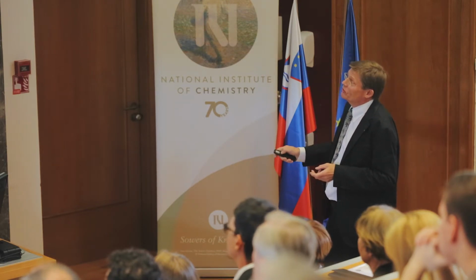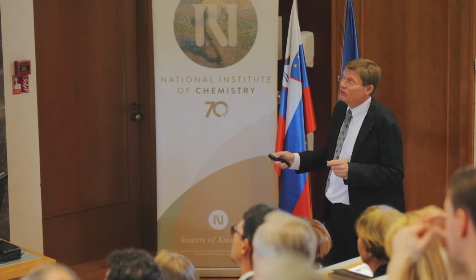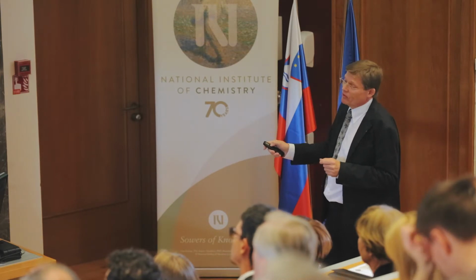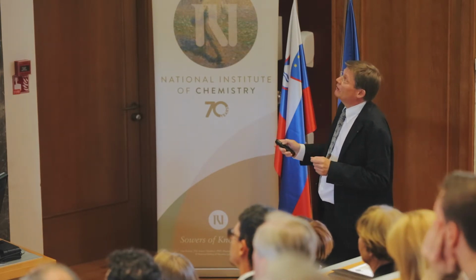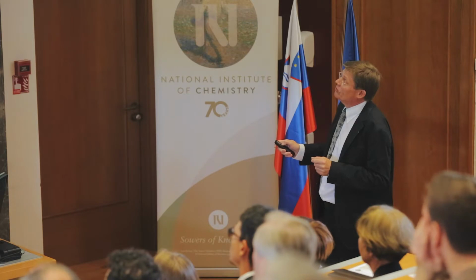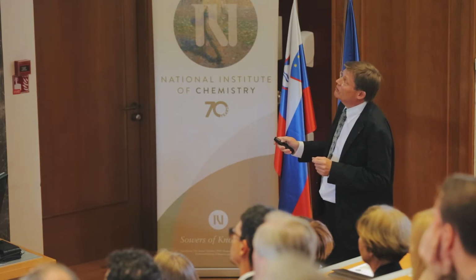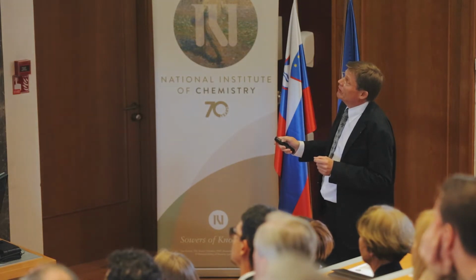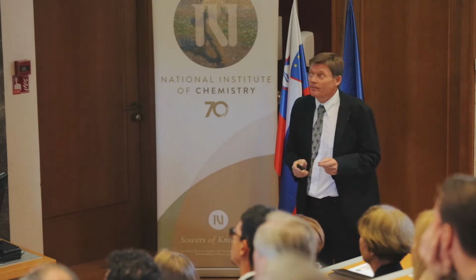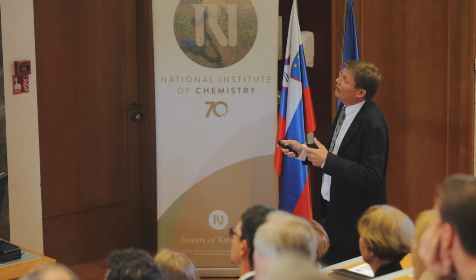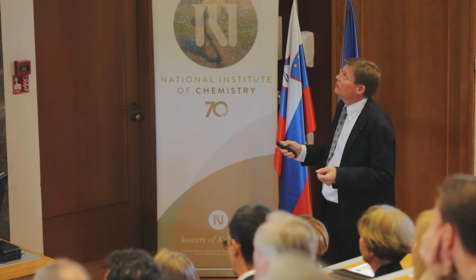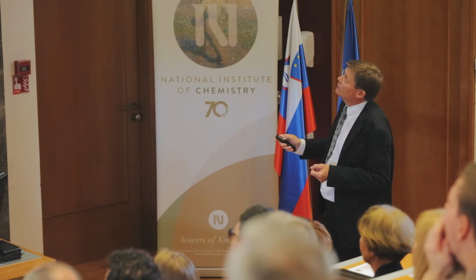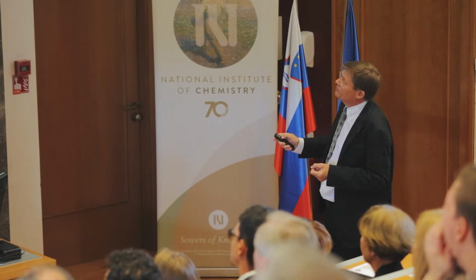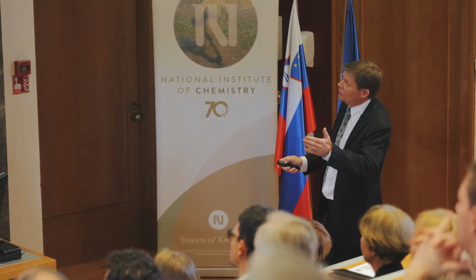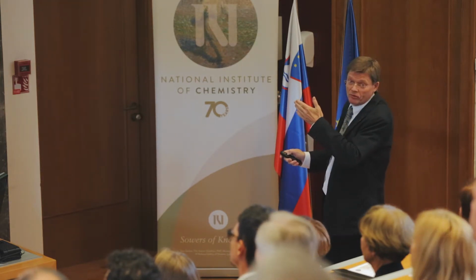And these are the strange diagrams. I don't want you to follow it. This is a normal defect diagram for perovskite. You don't have to deal here with oxygen vacancies, you have iodine vacancies. These iodine vacancies are the ionic carriers. Then you have electron vacancies, the holes, to consider. And you change here when you go through the phase with the iodine partial pressure.